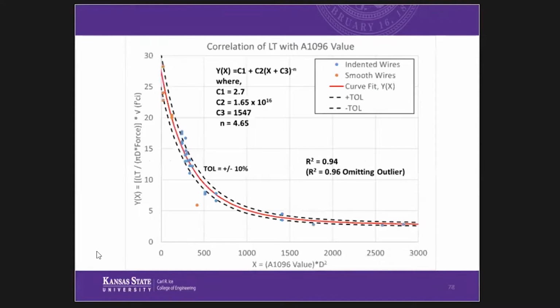And we actually are getting fantastic results. This is correlating with the ASTM pullout value. Now, these we'd expect to be excellent because if there's any changes in the lubricants, we're going to pick that up because we're marrying that with a Portland cement concrete and doing a pullout test.